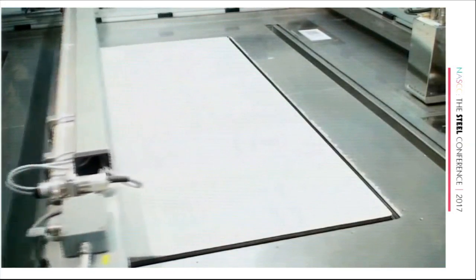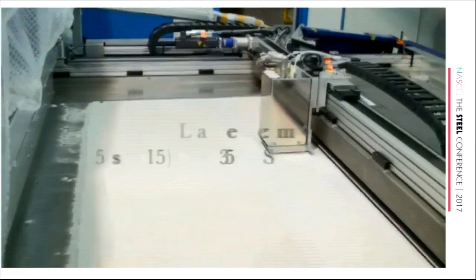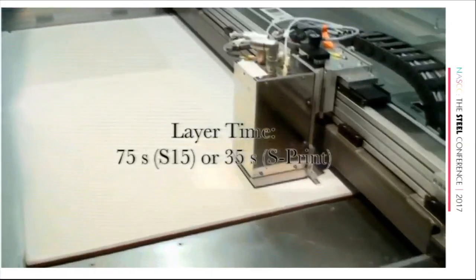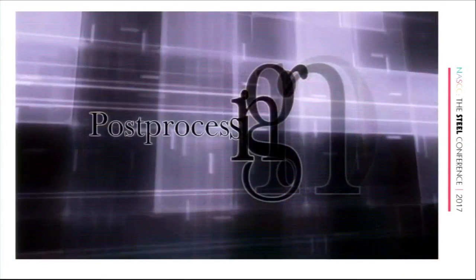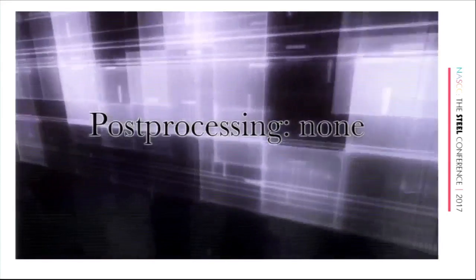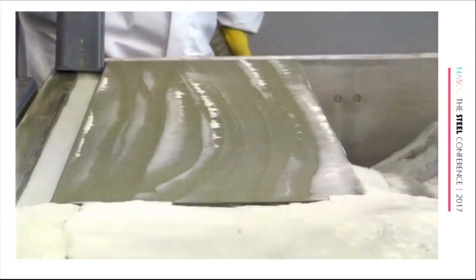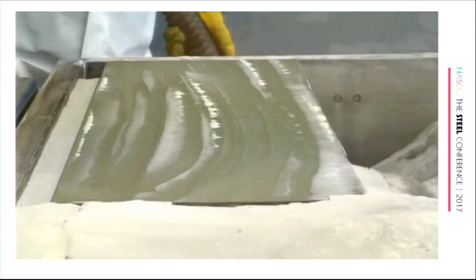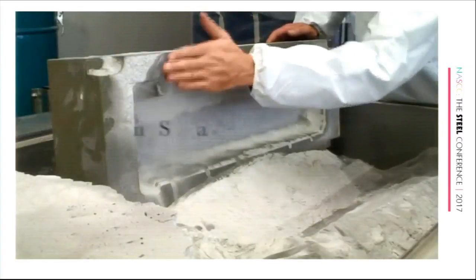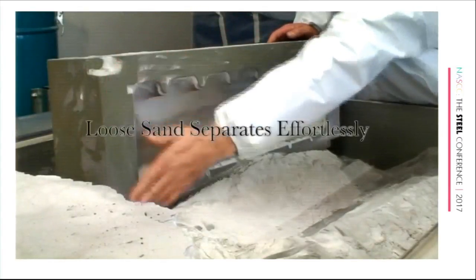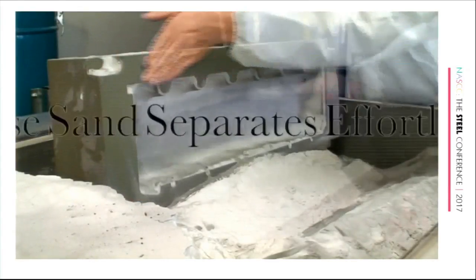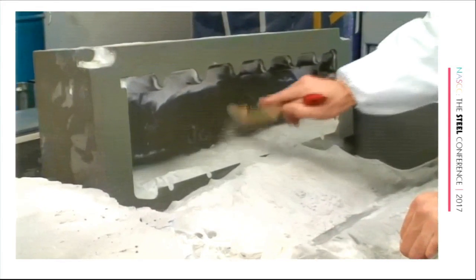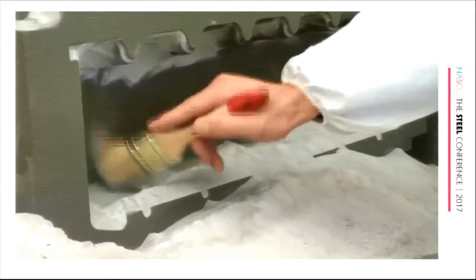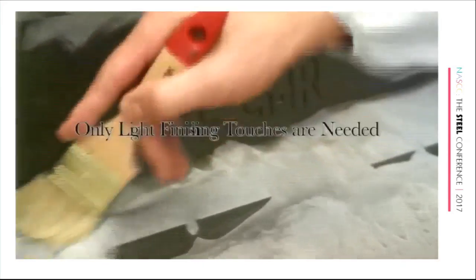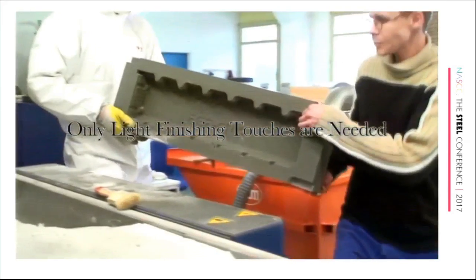This is a printer head, and basically you put a layer of sand down and then you print the binder on it. And after you print the binder on it, then you can vacuum out all of the sand that's loose and get the mold you want so that you can make the most complex parts. So instead of now having to pay for tooling, we can make parts in a week, in 2 weeks, if you really want to pay the premium to get those prototypes.